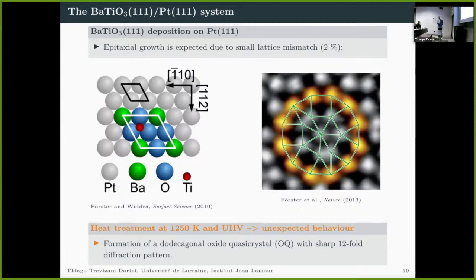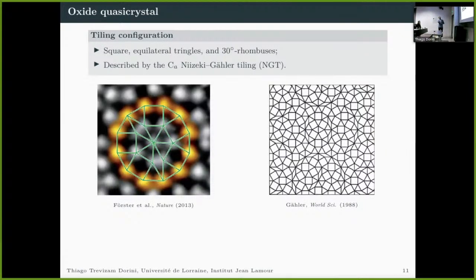And it's interesting to note that it has a sharp 12-fold diffraction pattern, as you can see here in the STM image, and it's composed of three tiling elements specifically. You can see it's composed of squares, equilateral triangles, and 30-degree rhombuses. And the structure of this quasi-crystal can be represented by the famous Niizeki-Gähler tiling, the NGT, as you can see in this image on the right.